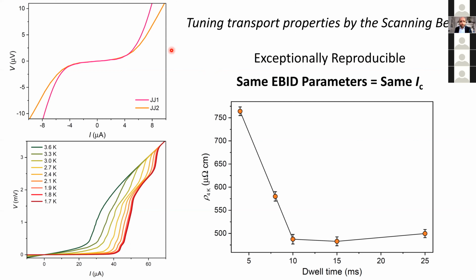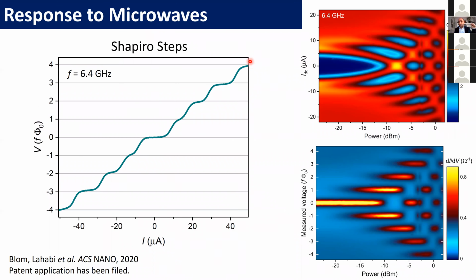But of course, here this is just a critical current. And the way to know that you've made a Josephson junction, because of course there's a big difference between having an inhomogeneous wire or having a Josephson junction, is to test it by irradiating your sample with microwaves. And in that case, this is a beautiful experiment. You'll see quantized steps in your current-voltage characteristics. And the height of these steps is simply the frequency of your microwaves times Planck's constant over 2e, the charge of two electrons.